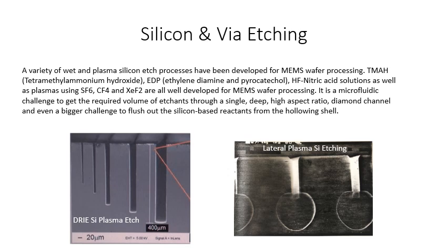Another really challenging step in fabricating the fuel pellet is etching away the silicon. We have decades of experience in etching silicon, both for integrated circuit fabrication and MEMS devices. Most MEMS devices have to have silicon etched, and there are some pictures that show examples of how silicon can be etched to make a MEMS device. Plasma etching can be used to etch very deep channels, just like the channel that needs to be etched in that carbon shell. After you etch down into the silicon, you've got to etch away the interior of that sphere of silicon, which is a challenge, and you've got to get that gas or reactant products out that very thin channel. That is a big developmental effort that had to be undertaken.